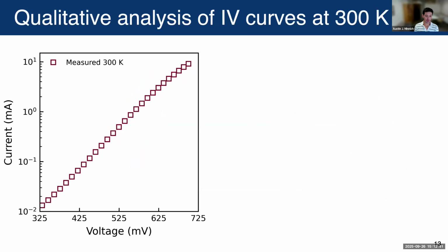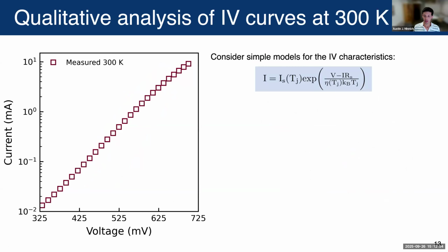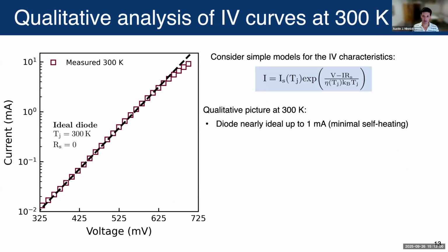Now, before we even do any formal quantitative analysis, even just by inspecting these IV curves, you can already learn a lot. So for instance, here's the IV characteristics at room temperature. And we can start with this model and kind of throw out all the complications and gradually add them back in. So to begin, let's ignore self-heating, let's ignore series resistance, and we actually get a pretty decent fit to most of the IV curve.